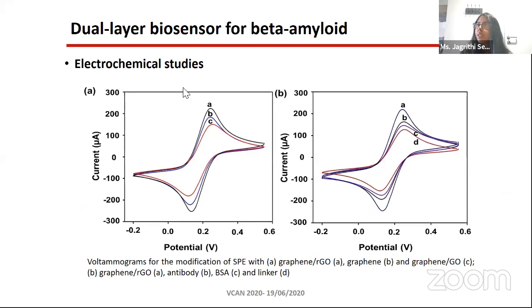Okay, so these are the electrochemical studies that we performed with our dual layer electrode. The first one is a voltammogram for the modification of a screen-printed electrode with graphene RGO. A is graphene RGO, B is graphene, and C is graphene and graphene oxide. So when you modify graphene with graphene oxide, the response decreases from B to C. There is a decrease in the electrochemical response. And then when we electrochemically reduce it to form graphene RGO, it again increases to show the maximum response. So it has high sensitivity compared to both graphene and graphene oxide structures.